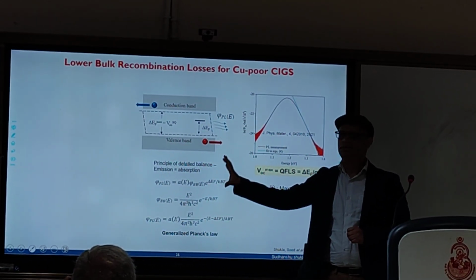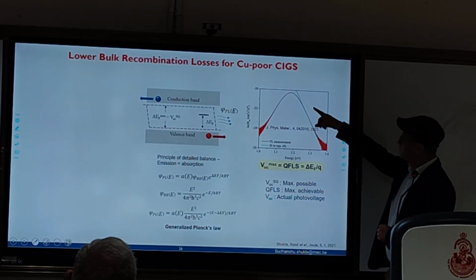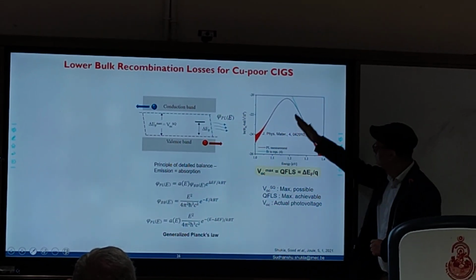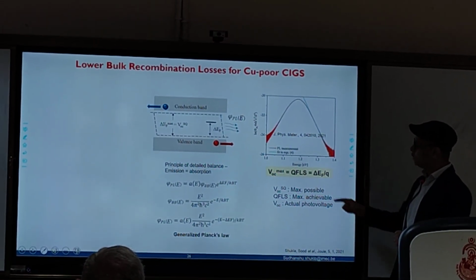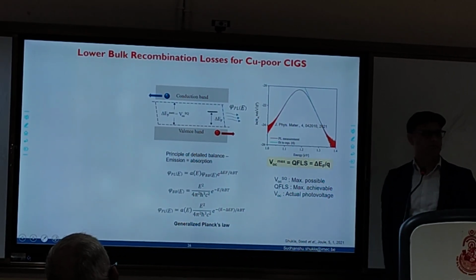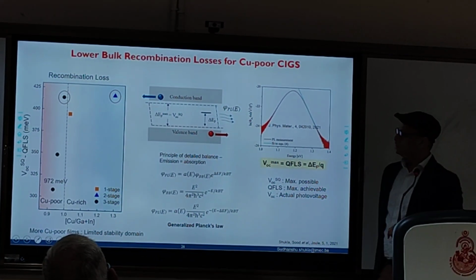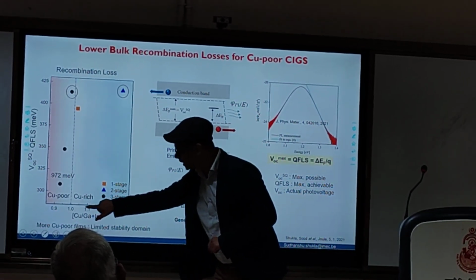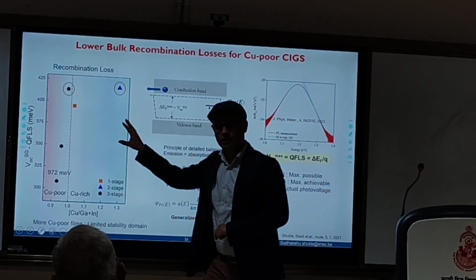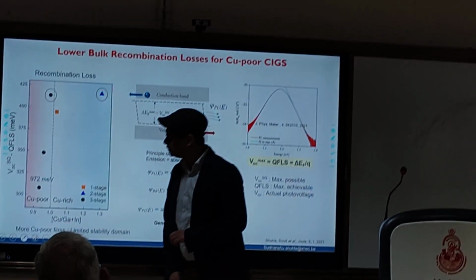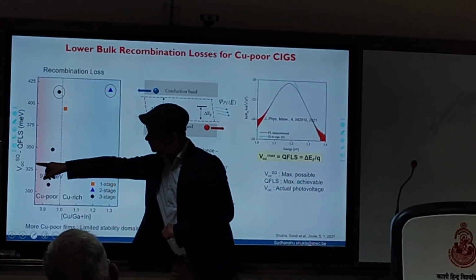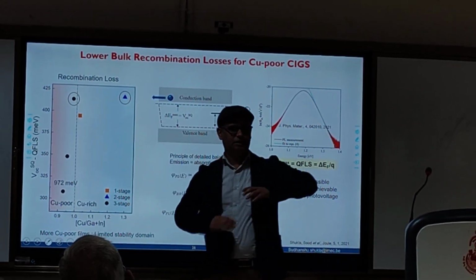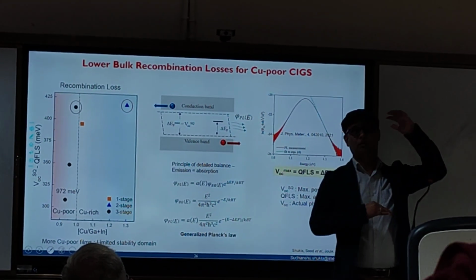The example is here, this is the photoluminescence. Using this relation, fit it, and you can find how much maximum VOC you can obtain. We did that, and look at this. This is the CIGS copper rich region. This is the region where things are copper poor. And the difference in VOC from the Shockley-Queisser is the maximum VOC you can get thermodynamically.